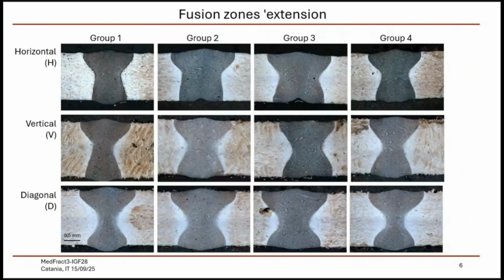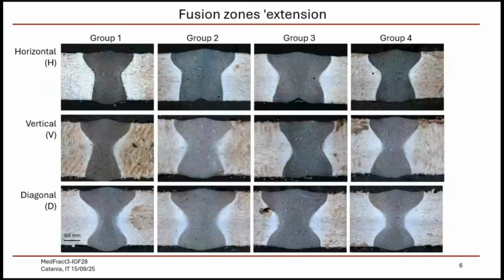So our 12 possibilities are represented in this matrix. The columns are for the combinations of process parameters, and the rows are for the building orientation. What is important to say is that the joints that we observed, all the regions that we observed, also with microscopes, are of good quality. So limited amount of porosity, some rare liquated grain boundaries, but no solidification cracks and no massive defects due to the welding process. So this was the important first result.